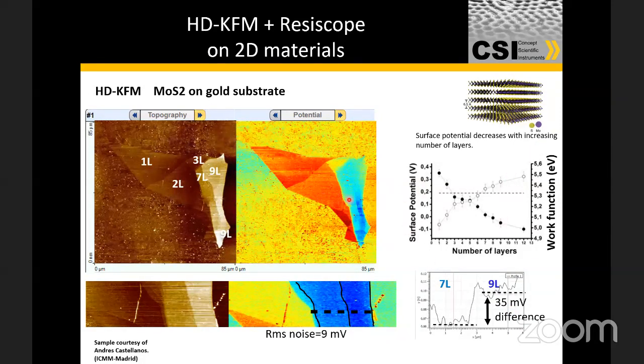Yeah, so what it is trying to tell you is that the surface potential decreases with increasing number of layers. So obviously you can see that within this flake itself, there are regions that have a certain number of layers, and there are other regions that have a higher number or a lower number of layers, right? You can see that from the topography itself, right?